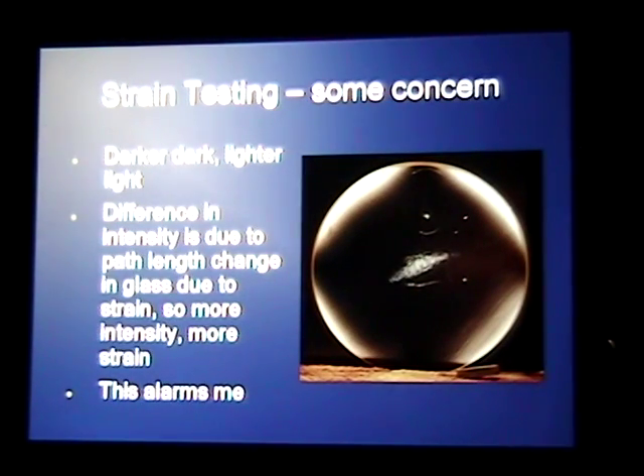Then we go on to something like this that starts to give me serious pause when it comes to working on it. We get very light, very dark, and it's got this four-sided symmetry. We're starting to form that dreaded cross that people talk about for very strained glass. Now typically with this stuff, what you'll see a lot of times is as the mirror cools, you'll see astigmatism in the images. That's one telltale sign, but it'll go away as the mirror cools off, and it will rotate with the mirror, but it just goes away as the night goes on and as you get equilibrated. So it's another sort of false astigmatism that's not actually in the figure. Now it can be polished in because during polishing, the heat will warm up the glass and actually cause it to warp asymmetrically. So there's a lot of possibilities here, and sometimes it's hard to tease out.